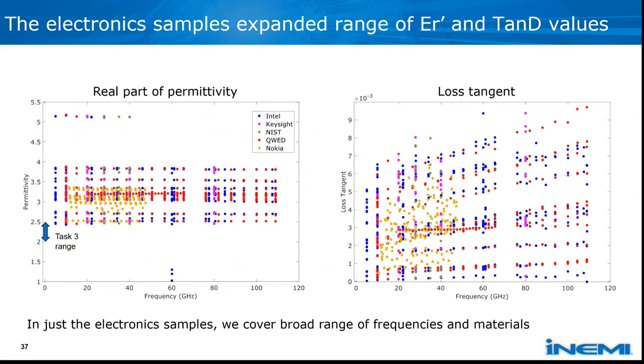Highlighted on the left is that task 3 range in the real part of permittivity, showing that for the COP and PTFE measurements we made in task 3, we really only covered real parts of permittivity between 2 and 2.5. In task 4 here, we show that we're going from overlapping with that range slightly all the way up to a permittivity north of 5. Additionally, on the right, you can see a huge range of loss tangents shown all the way from 1e-4 to about 1%, which is a tremendous spread. So just in the electronic samples, we're covering a huge range of frequencies and material properties.